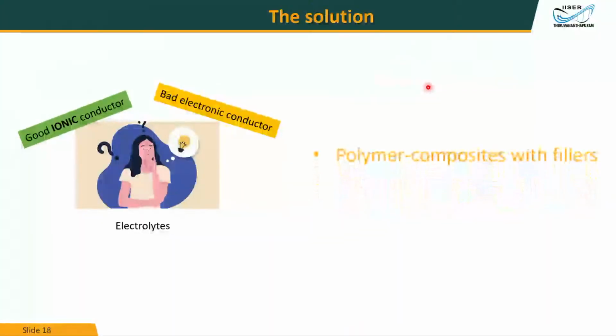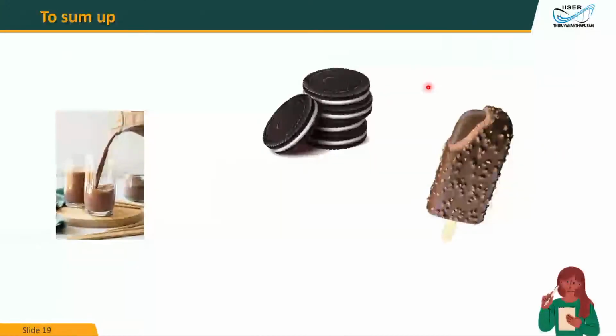So lithium or sodium or potassium are good anode candidates. You cannot use them because of this issue of dendrites easily going through these liquid electrolyte systems. So we need to replace the liquid with another electrolyte medium such that we restrict the flow of these dendrites. So we need better electrolytes. One option is a composite polymer electrolyte with fillers, and the other option is inorganic materials like ceramics and glassy materials.